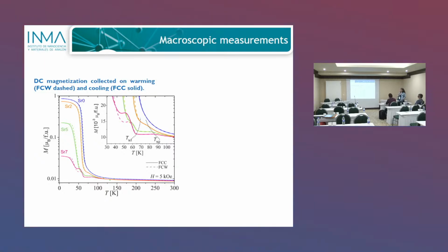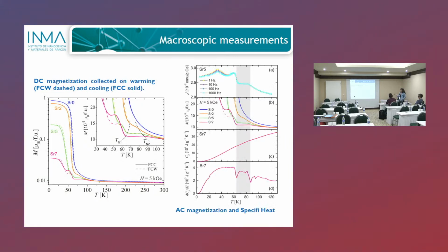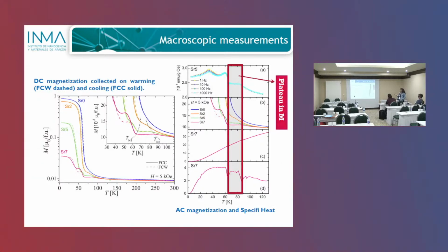introducing these kinds of behaviors with a hysteresis here and a plateau, which I highlight better in this figure. You can see that there is a region between 62 and 82 Kelvin approximately, where something else is going on, and the magnetization starts to get flat.